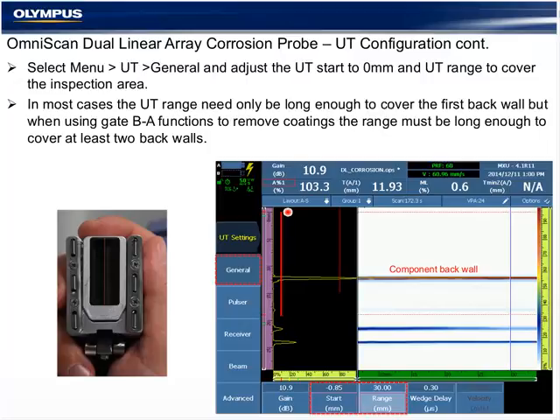That typically inhibits near surface resolution and results in an interface signal right at 0 millimeters. This is true for all conventional and phased array probes that are transmitting from one side of the array and receiving on the other. Like a conventional UT probe, the benefit of that is to remove the surface echo that impedes near surface inspection for pitting and thin resolution, a better SNR.